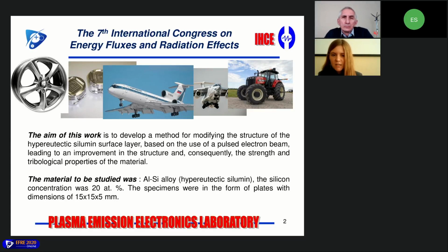But also modification can lose its positive effect by addition of large amounts of modifier, which is called over-modification, and which often causes the formation of brittle compounds which degrade alloy performance. And also, at the same time, the cooling rate has a marked effect on the size, morphology, and distribution of all microstructural constituents.